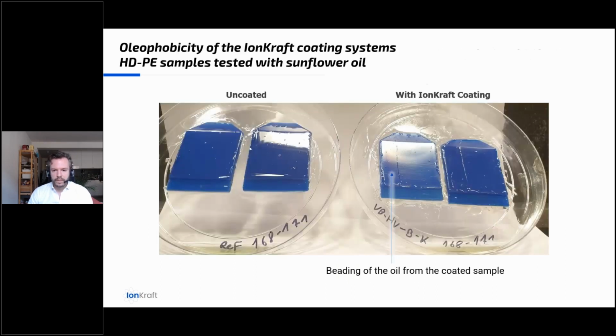So here you can see a demonstration of the oleophobic properties of our coating systems. The left samples are uncoated, while the right samples are coated with our coating system. And what you can see clearly is how the oil is dripping off and beading off of the coated sample, while the uncoated sample remains fully wetted. This implies that with any kind of oil packaging, you will have an easy to pour solution, and you will get all the residue out of the bottle, which is a huge impact factor also for the recyclability of the container in the end.